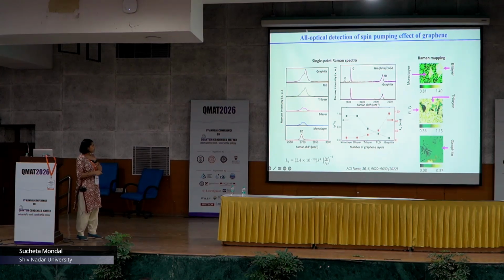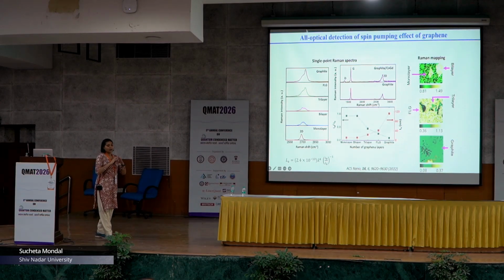We have characterized these properties, including how the defects evolve from Raman mapping, and we have also calculated the defect density. We have basically characterized how good or bad our films are. When we did not sputter a ferrimagnetic layer on top of the graphene, the defect peak did not arise, so we feel our exfoliated graphene was clean and atomically more or less defect-free. But when we bombarded it with ferrimagnetic ions, co-sputtering cobalt and gadolinium separately, defects appear.